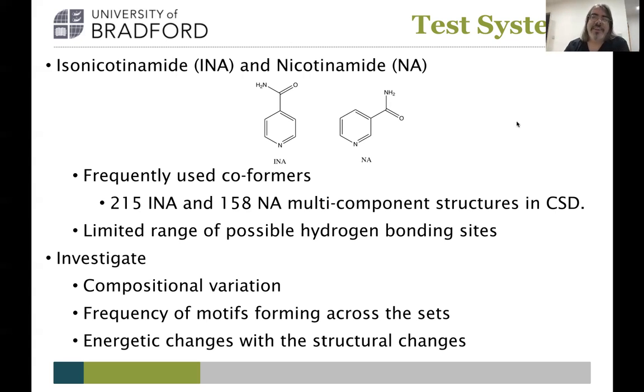The other advantage in this study is that they have a limited set of possible hydrogen bonding sites. So for our studies of competition, we've narrowed it down to really only two. The nitrogen in the pyridine ring can accept from acids, hydroxyl groups and other hydrogen bond donors, and our amide group can donate and accept together. And the other nice thing is that we have the same groups, but in different geometric arrangements. So there's a nice question about how that affects the ability to pack and the sort of structures we can see. So what I've looked at is compositional variation across these systems.